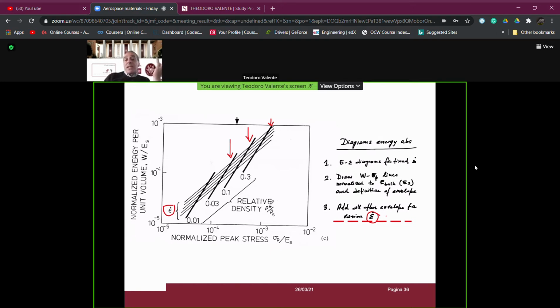And then we have finished, because we have all three parameters on these diagrams, which let us define the mass density of the solid, depending on the normalized peak stress that we want, and depending on the energy per unit volume that we want to absorb. Again, I repeat, normalized to the bulk Young modulus, that is the Young modulus of the corresponding bulk material. And this is a graphical procedure.